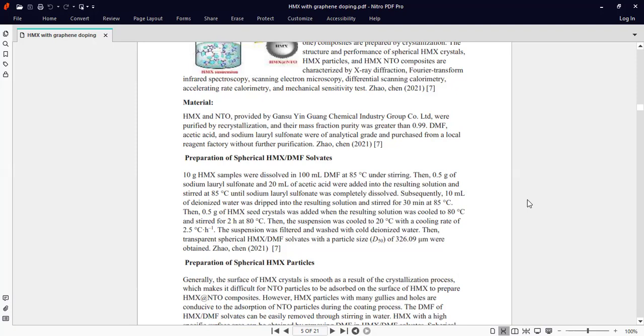Preparation of spherical DMF solvates. 10 gram of high melting explosive sample was dissolved in 100 ml of DMF at 80 degrees Celsius under stirring. Then 0.5 gram of sodium lauryl sulfonate and 20 ml of acetic acid were added into the resulting solution and stirred at 85 degrees Celsius until the sodium lauryl sulfonate was completely dissolved. Subsequently, 10 ml of deionized water was dripped into the resulting solution and stirred for 30 minutes at 85 degrees Celsius. Then 0.5 gram of HMX seed crystals was added when the resulting solution was cooled to 80 degrees Celsius and stirred for 2 hours at 80 degrees Celsius.